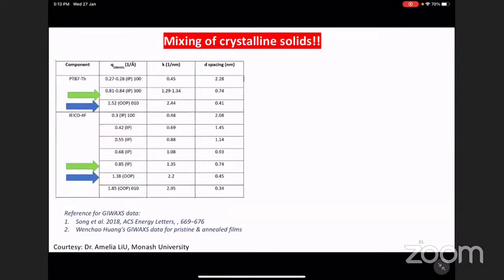Same thing is when we moved from the fluorine to non-fluorine, the challenges came. There, all the things were happening by the fluorine long-range ordering. But here we have the ordering because of both. And peaks associated with those ordering are more or less in the similar range, which basically suggests some mixing of the crystalline solids, which is a very new thing. I haven't seen much in the literature, at least in the organic semiconductor community, on how to mix two crystalline solids on the lattice level.